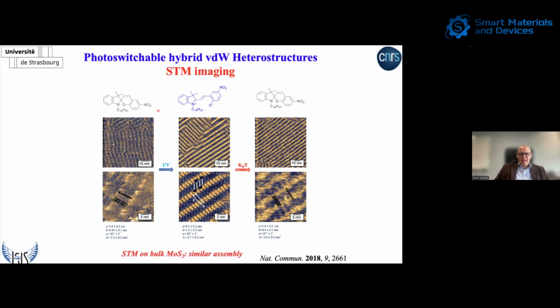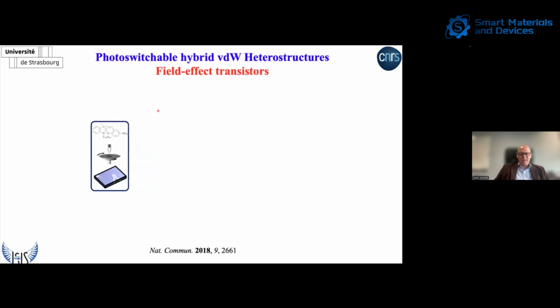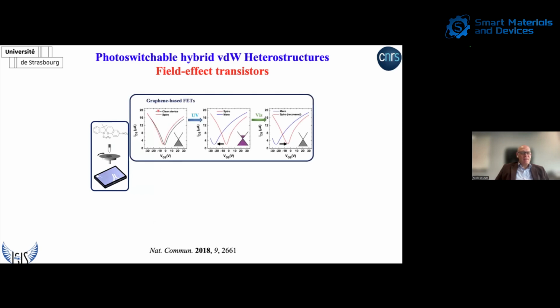And then we fabricated devices, a back-gated field effect transistor, and you can see here the idea is that we have in black the clean device, so it's pure graphene. Upon physisorption of the monolayer of spiropyran, we have a very small n-doping effect. Then upon UV light illumination, you can see that this n-doping becomes major. We obtain this blue curve, which is totally reversible upon visible light illumination. So we have a reversible doping effect that can be quantified.